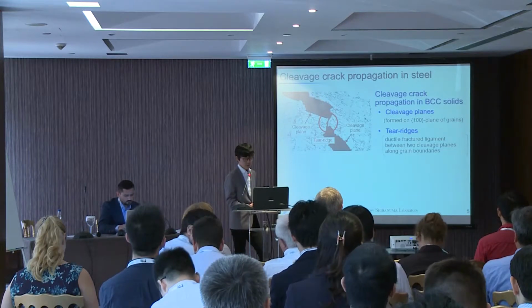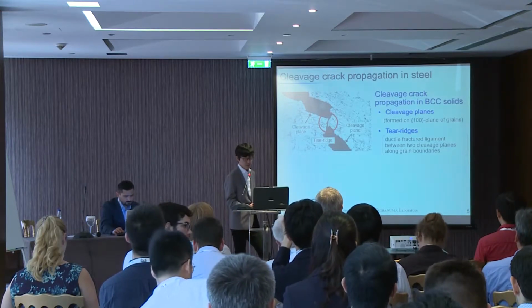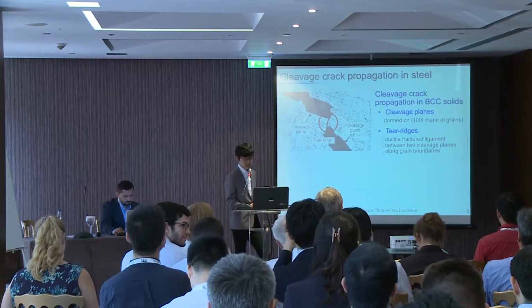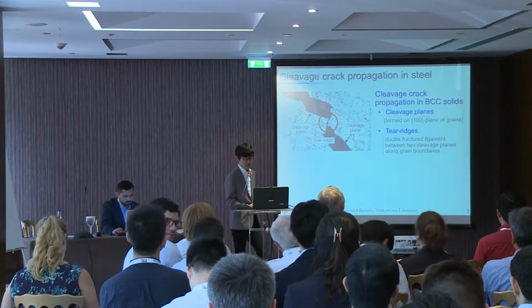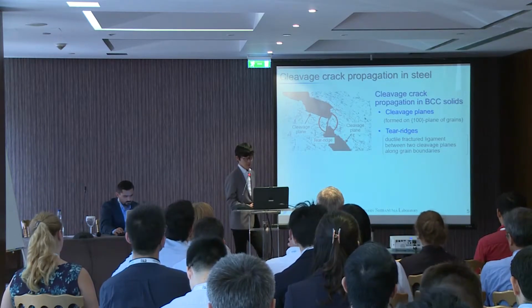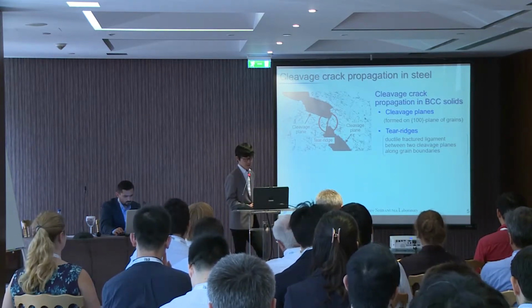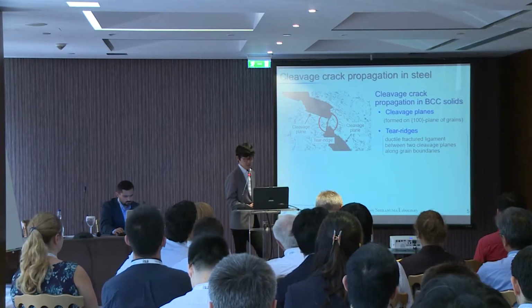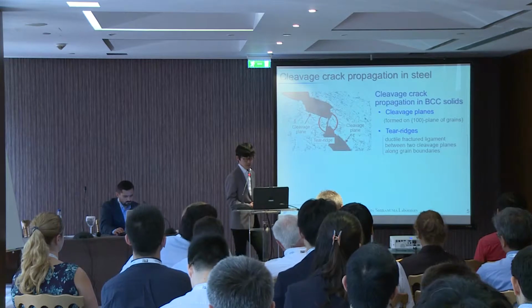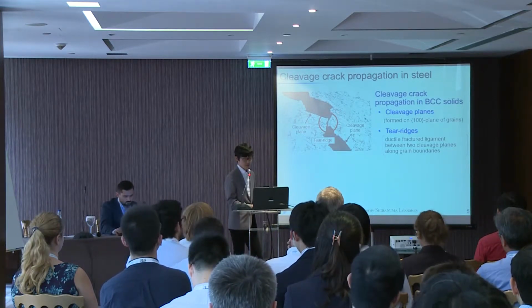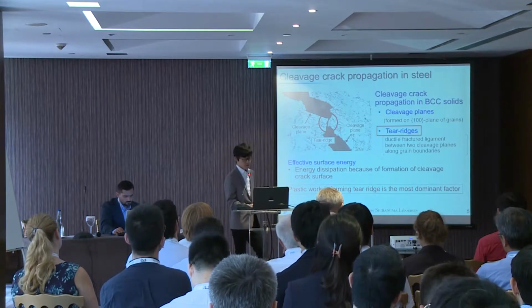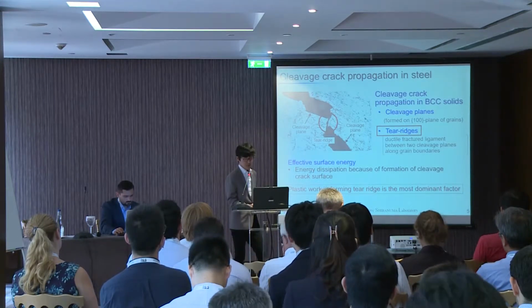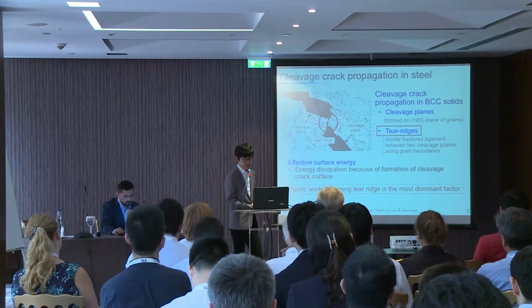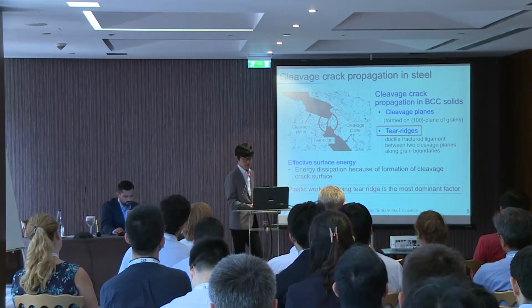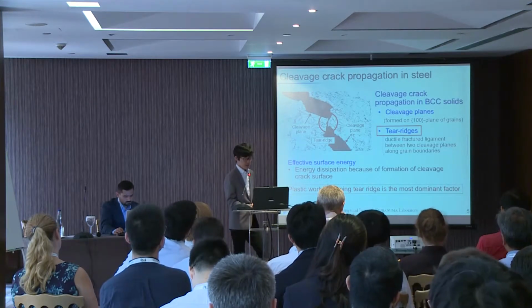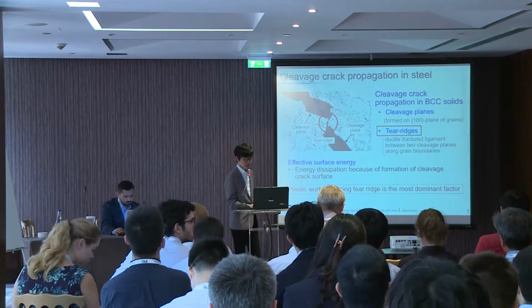There are two types of cleavage crack propagation in BCC solids. One is cleavage plane, and the other is tear-ridge. Cleavage planes are formed on 100 plane of grains. And tear-ridge is a ductile fractured ligament between two cleavage planes along grain boundaries. And we focused on tear-ridges, because from the viewpoint of effective surface energy, that is energy dissipation because of formation of cleavage crack surface, plastic work in forming tear-ridge is the most dominant factor.